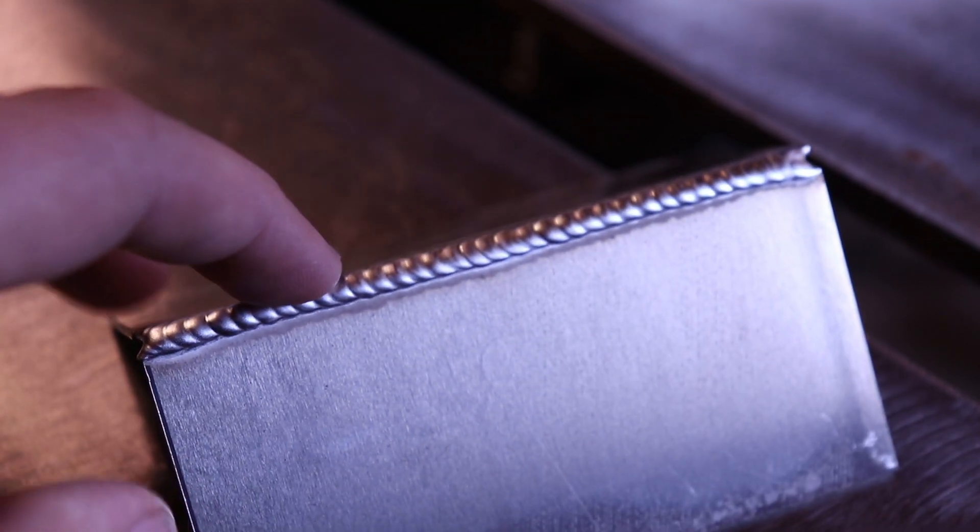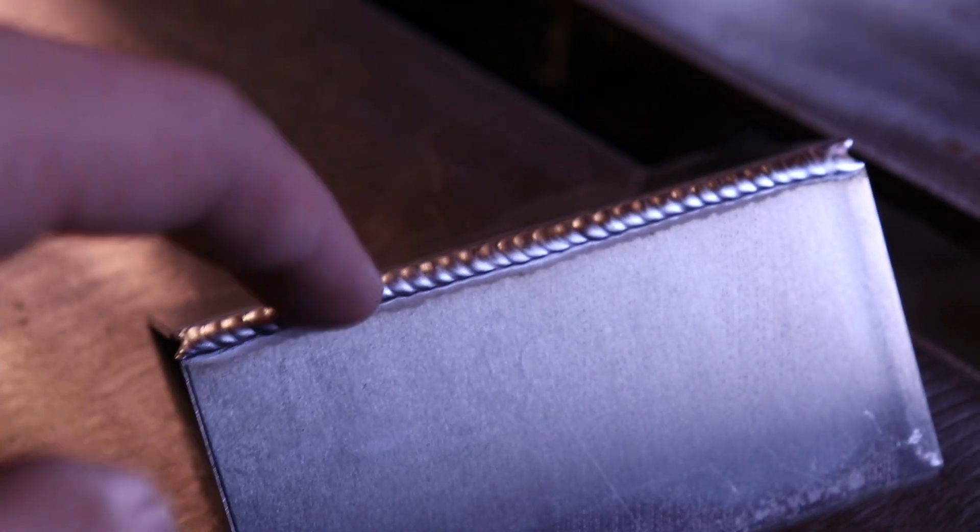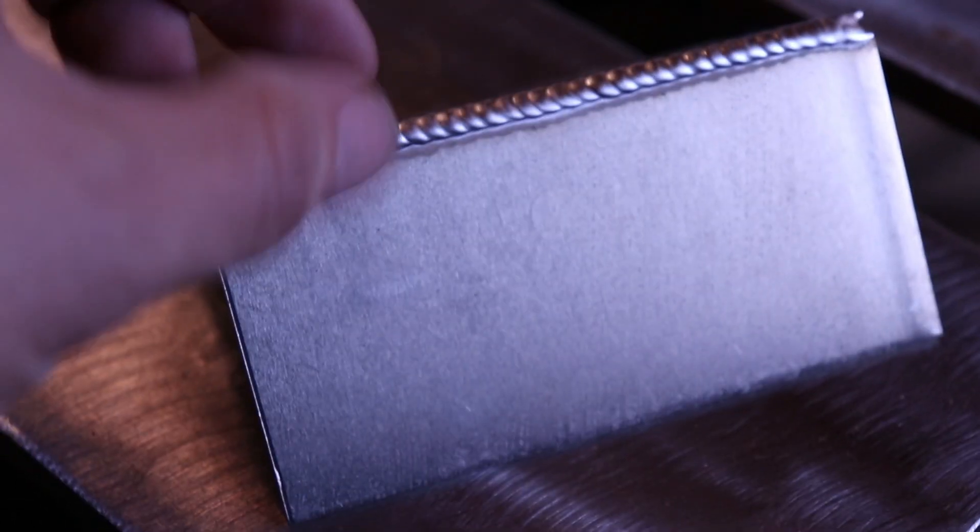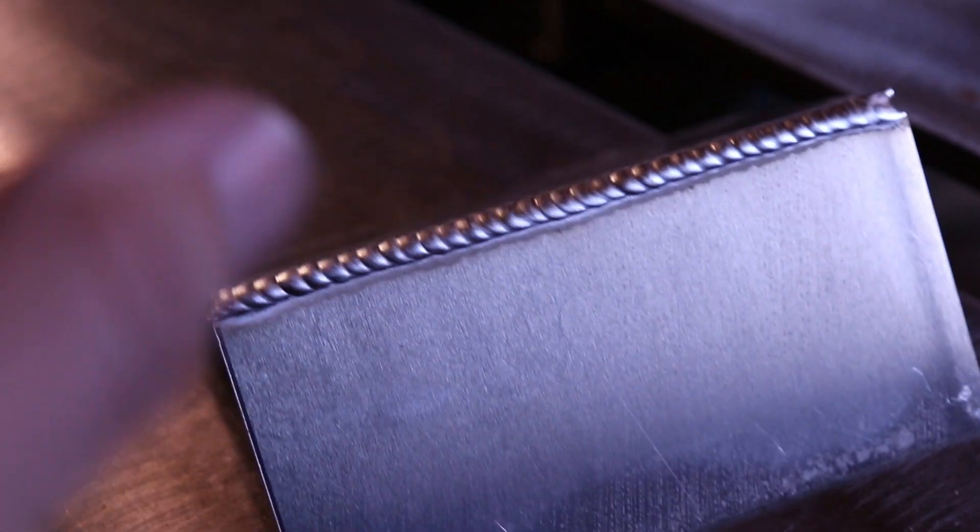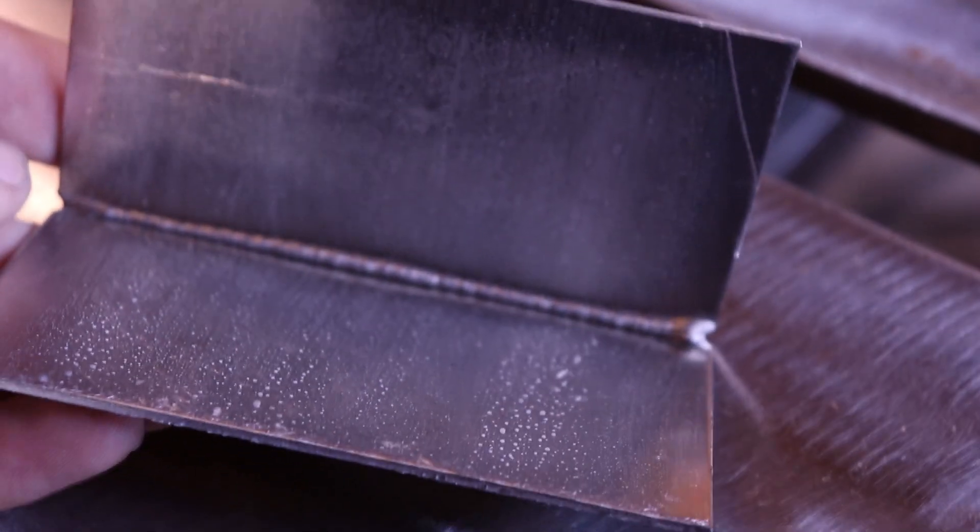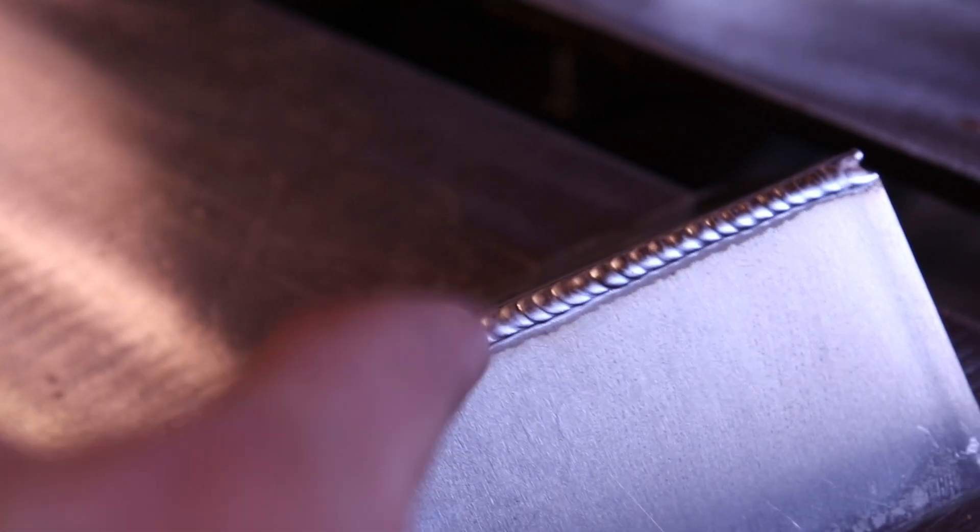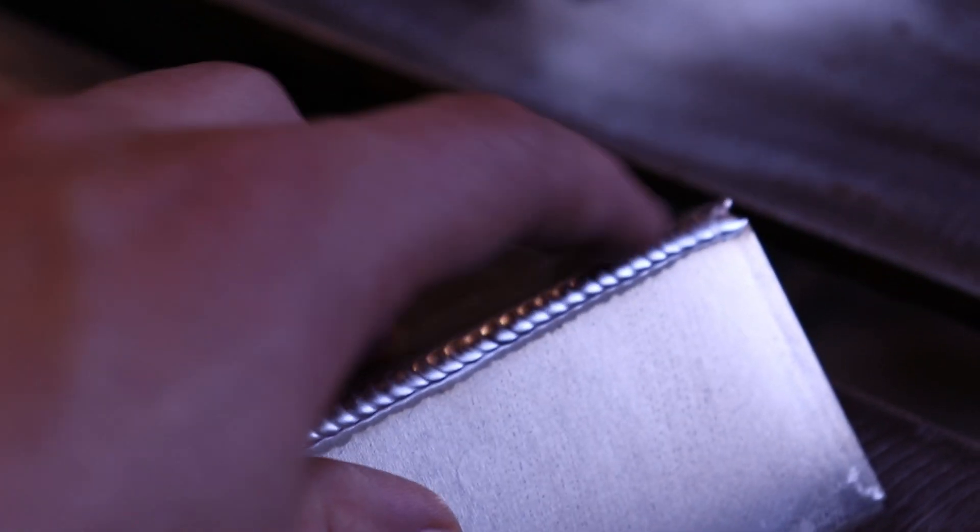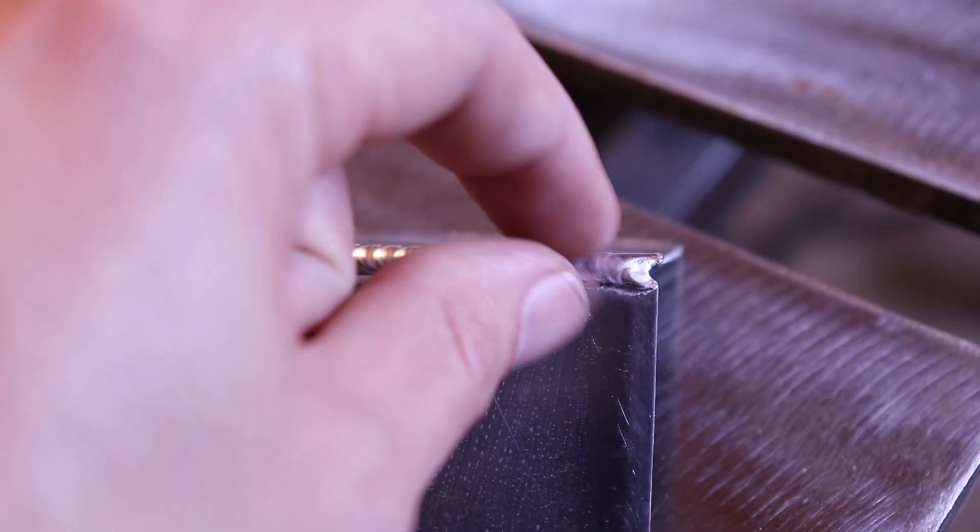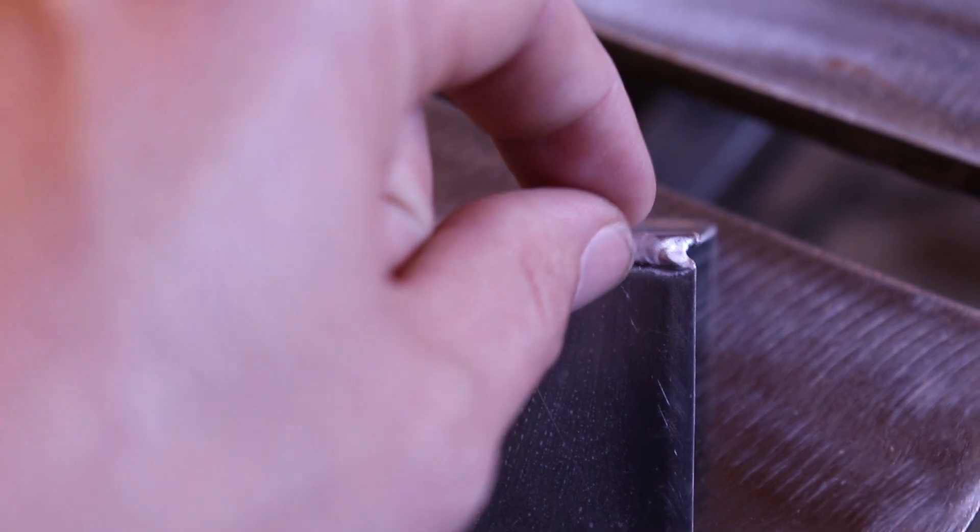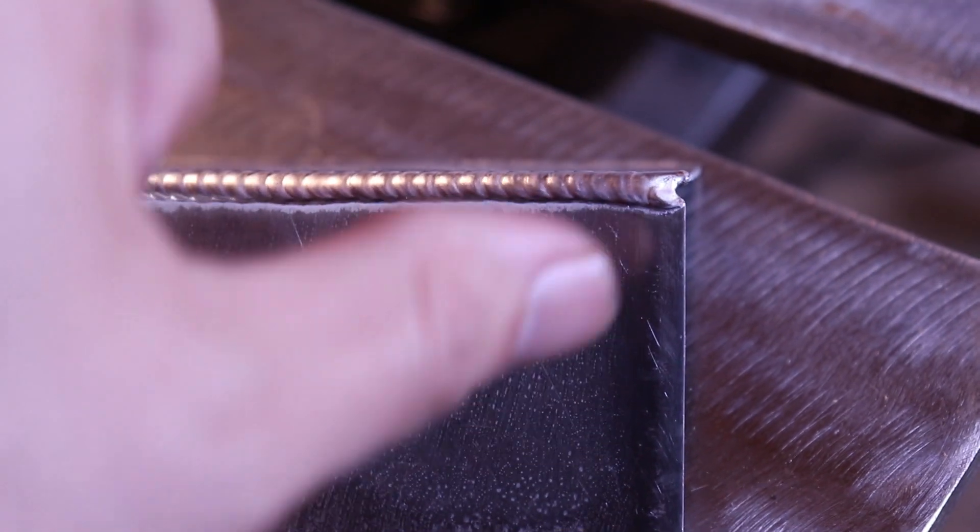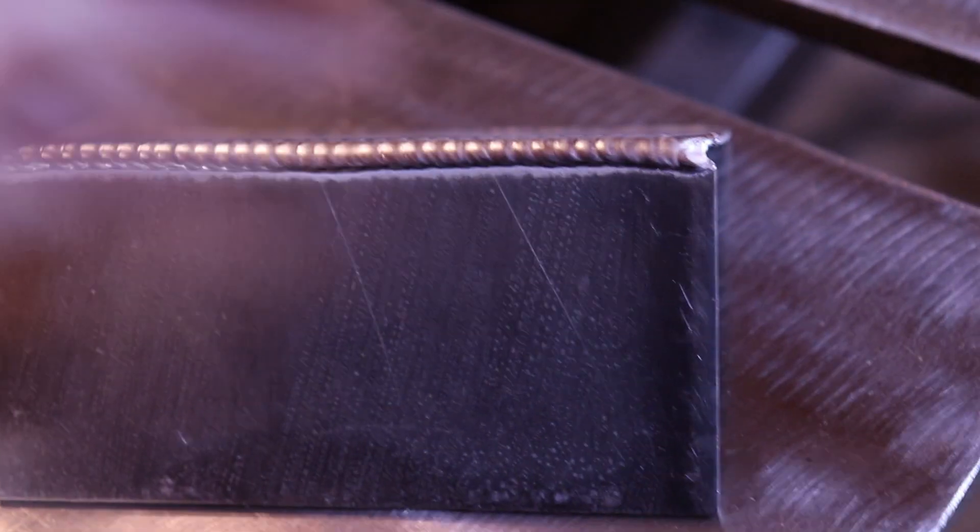I welded this on two different settings. I like to use 90Hz on my outside corners but I accidentally left it on 200Hz and it seemed to do alright because it doesn't have to wrap around that much. So that's what I used on this. There's penetration on it. And on thinner stuff you gotta run a lot faster because by the time you get to the end it starts to fade out. If you watch back on the arc shot you'll see that it's not flowing together right at the end and that's actually because it's heat soaked right there. So if you go back, rewind just a little bit and watch that you'll see that it's not coming together and that's a sign that you're getting heat soaked. Even though you add more pedal on it, it's not coming together, that's because it's heat soaked.